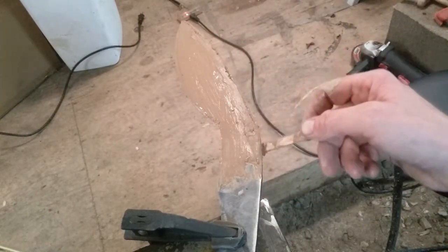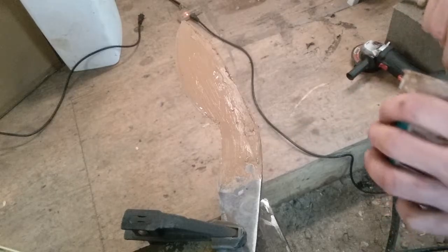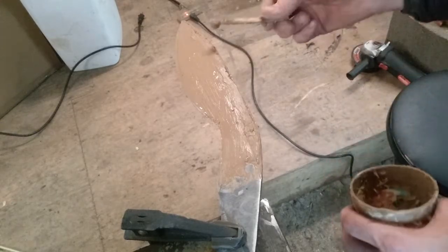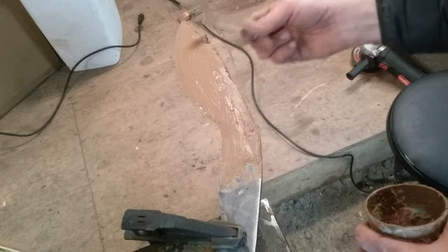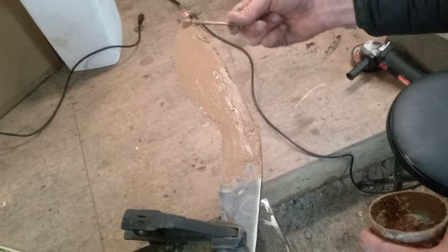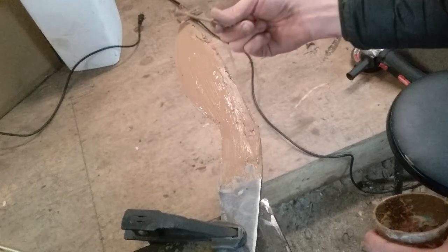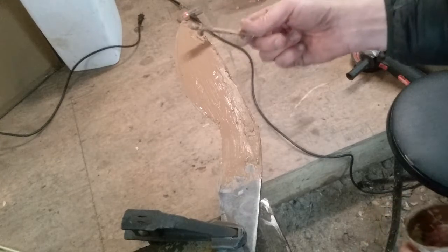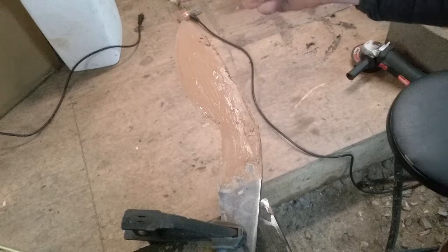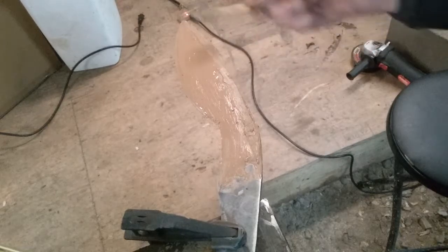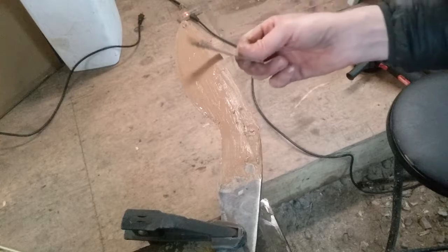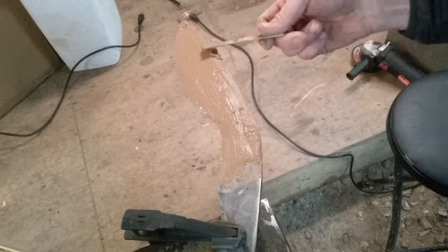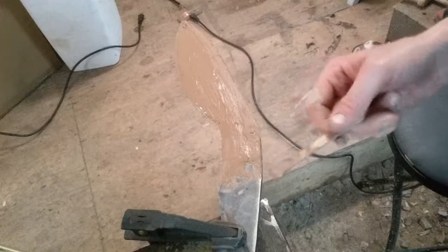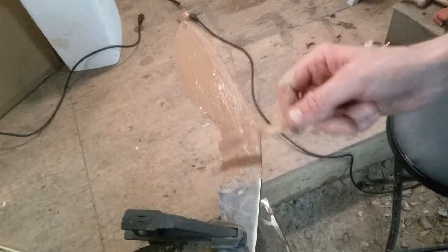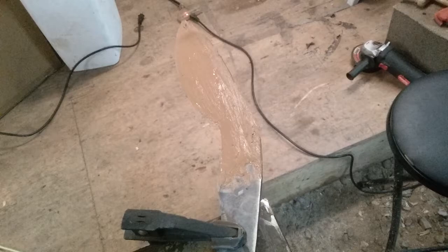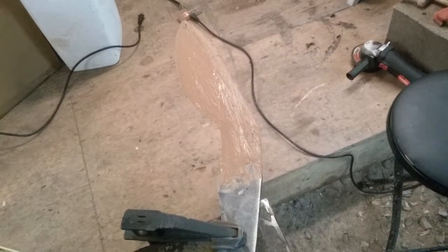Or add a little clay to a place that is a little thin. I can build this up here a little bit and then come back, just smear it a little bit. I can also clean that up once it dries a little bit and smear it out. You'd be surprised how quickly this clay goes back to wet, even if it's dried. Now, once it's been fired and baked on, it's hard as a rock. It becomes basically like pottery. And then you will not wet it anymore. Okay. And that is my clay.